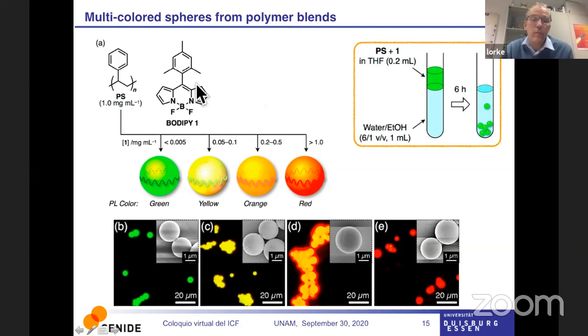That's used in biology and in chemistry a lot. Turns out the color that the spheres get when you make polystyrene spheres that are dyed with BODIPY depends on the BODIPY concentration. If you have a low concentration, they will look green, like you see here. Higher concentration, yellow, orange, or even red if the concentration is more than 1 milligram per milliliter. This is how they make it. It's a slightly different process. You have, again, the good solvent and the bad solvent, and then the solvent exchanges here in the liquid, and the polystyrene with the BODIPY precipitates in these nice spheres, as you can see down here.